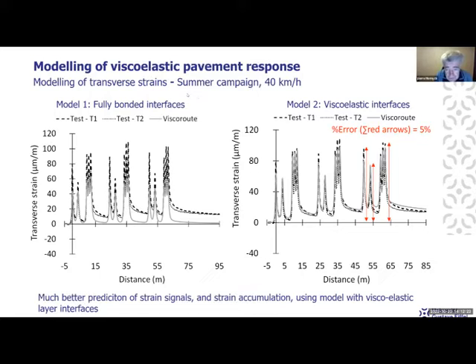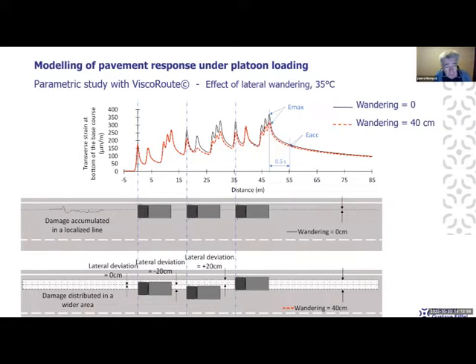And then we tried different assumptions, and we found that if we also model the interfaces as thin viscoelastic layers, we can get a much better reproduction of the measured strains, and we can get both the effect of strain increase in the second and third vehicle, and also the slow strain recovery after passage of the trucks. So we get much better results with the model with viscoelastic layer interfaces. And we calibrated this model on the measurements. And then in the second phase, we also used this model to make parametric studies to see the influence of different parameters. So here you have an example.